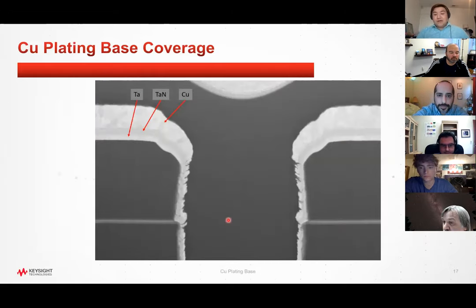So here's an example of what some of my work would look like when we deposit and take a cross section. Here's that copper seed layer. And in our case, we use tantalum nitride and copper. But you can see here's our via structure. And as you get to the sidewalls, it doesn't look too great. You've got all these gaps. And ideally you want to optimize to have as smooth of a sidewall covering as possible.